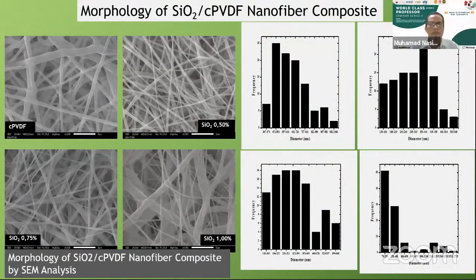This is the result of our research. This is the separator based on the silica co-PVDF nanofiber composite. You can see this is the pristine co-PVDF polymer. By adding the silica, the diameter of the fiber decreased. From this result, we can see the optimum composition formulation is 0.5% of silica. We can make a very thin and homogeneous nanofiber.